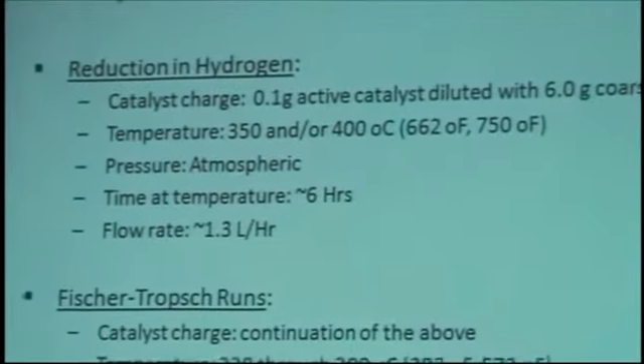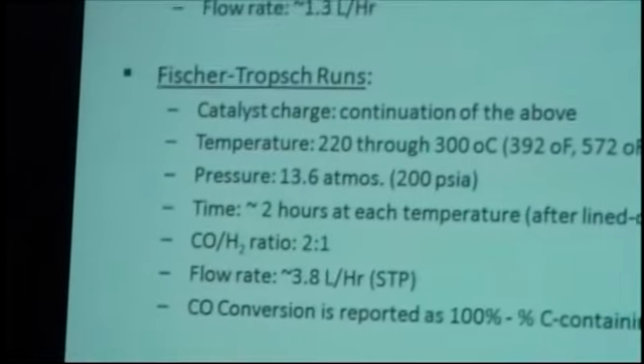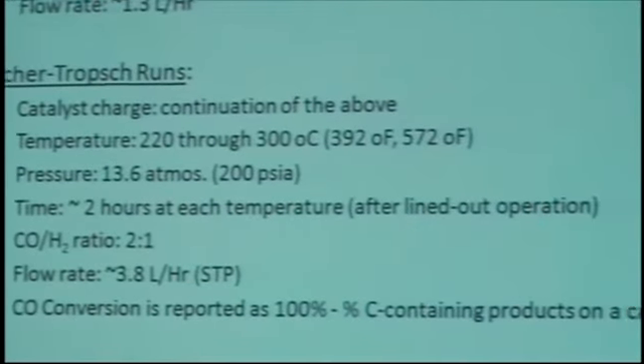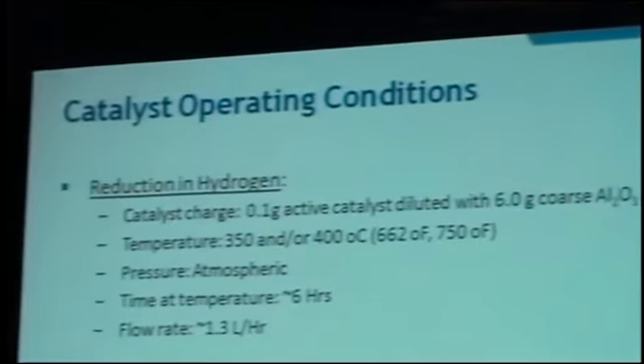The reduction step is exceptionally significant in using the cobalt catalyst. The original concept was to do it at 350 C, wait a while, it'll work beautifully, and make whatever runs you want to make. It didn't work out that way, and that's the reason why we bent the project in this way. For the reduction phase, the catalyst charge was 0.1 grams, blended with coarse alpha alumina to dissipate the heat and spread it over a little bit of the zone of the reactor. Temperature was 350 C or 400 C, at atmospheric pressure, with about 6 hours at temperature. It takes about an hour to get up to temperature. Flow rate is kind of incidental; it's a 100% hydrogen feed.